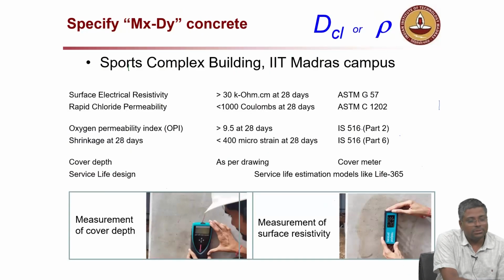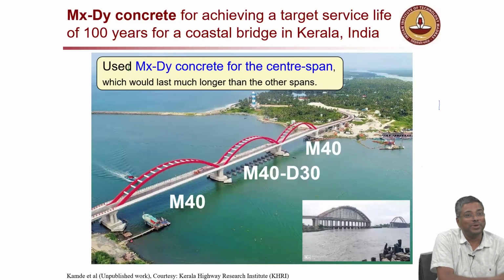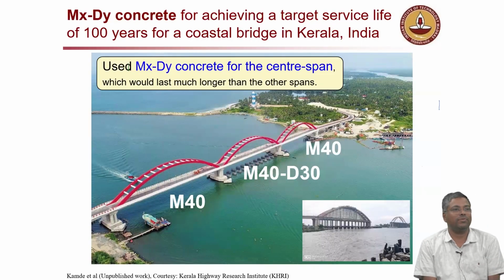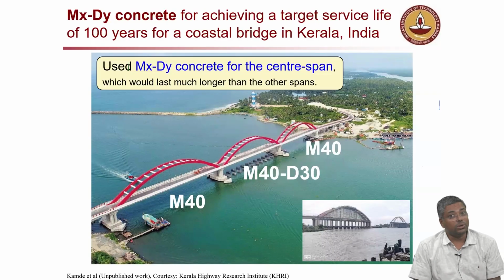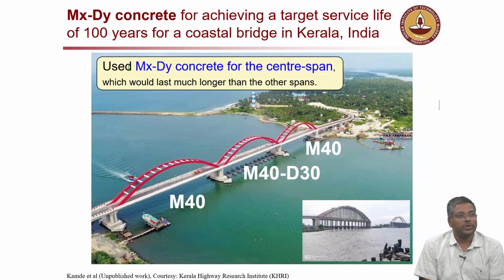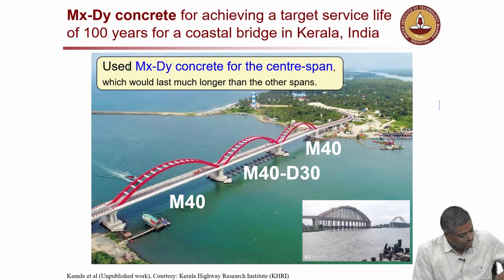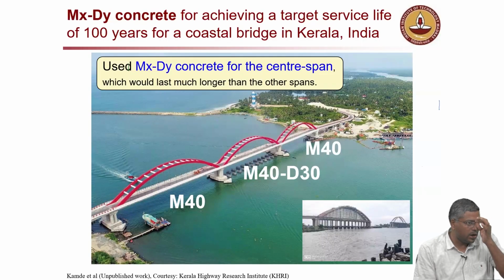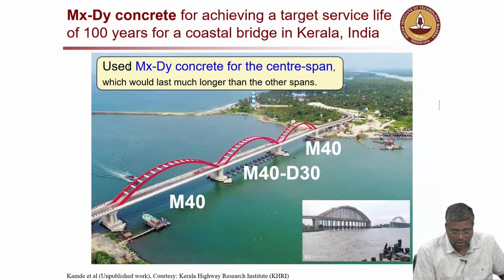Now at the site, you have to really worry about it. How do we achieve that wet condition? So we are saying, spray water and keep it wet for 30 minutes or so. That also depends on the type of concrete. If it's very impermeable concrete, 30 minutes may not be enough. If it's porous concrete, 30 minutes is enough. So there are a lot of things. It's not very simple, but we have to define the condition. Measurement on dry concrete will not help. You will get a very high value, but that's not what we really want. When does corrosion happen? When the concrete is wet or when the concrete is dry?